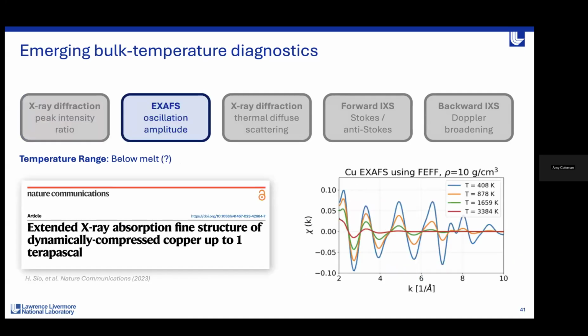Another technique, obviously, is XAFS, as we've discussed. Here, finally, is the reference to Hong's paper - this nice work I was talking about earlier on measuring temperature in copper. This is the one where we saw the increased heating from the diamond sandwich. It's a fantastic, fantastic paper, really nice work. Again, it shows the dropping of the amplitude of these oscillations as we go up to high temperatures. This technique does rely on QMD simulations in the way that we interpret the temperature here, so it does rely on a model.